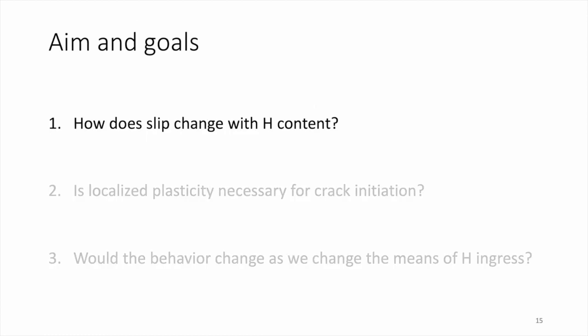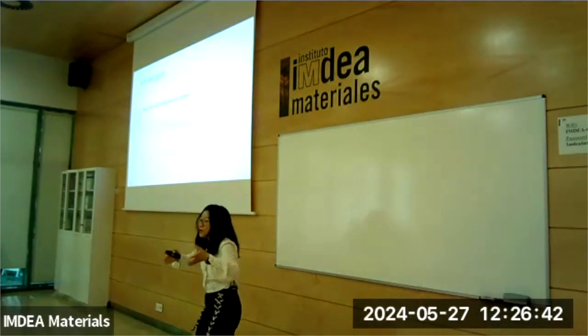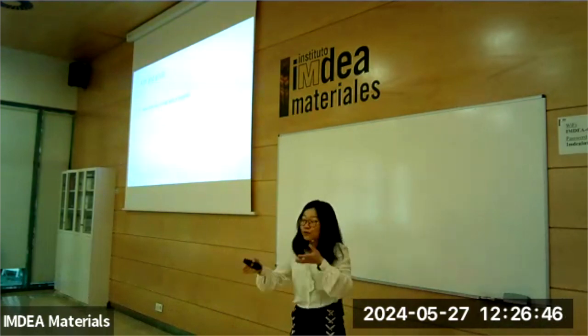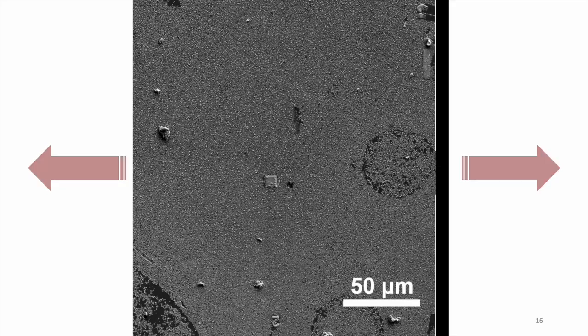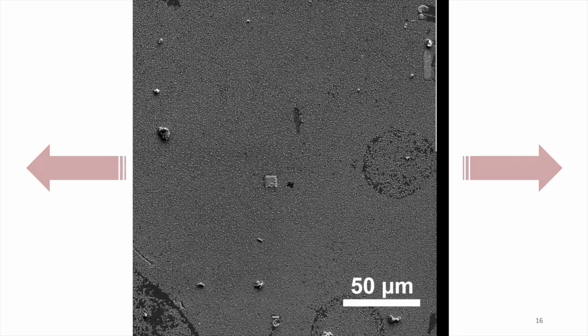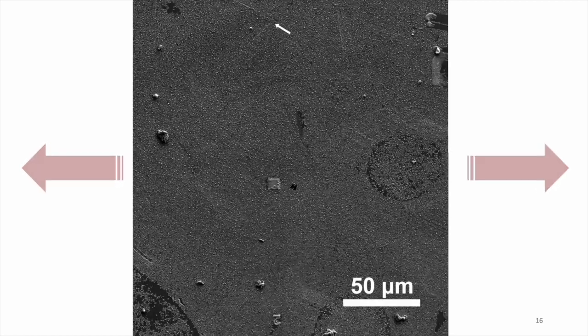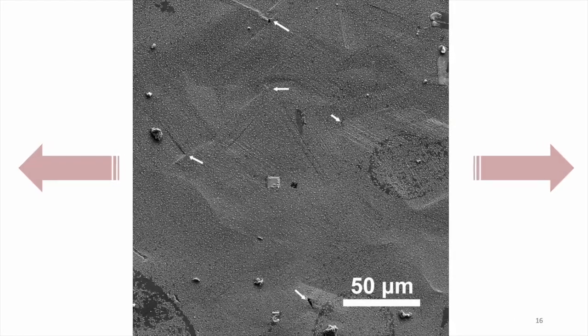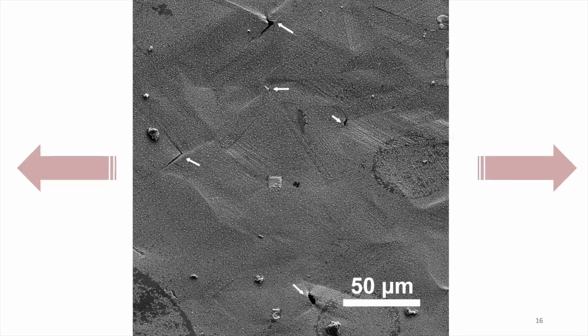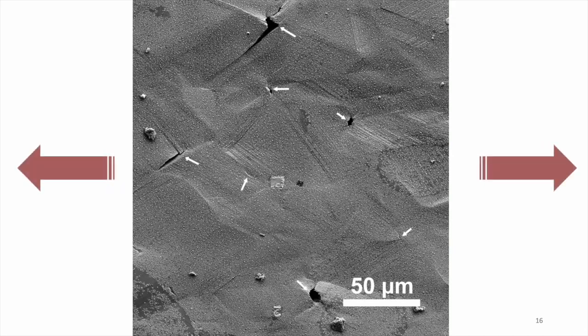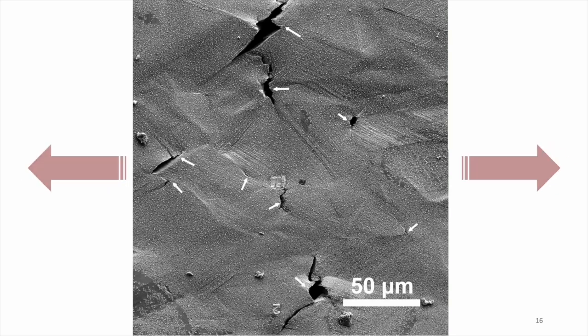Going back to our main goals, we want to know how the slip changes with hydrogen content. We know we can see surface slip under SEM, and we see more surface cracks in the electrochemical charged sample. So to better understand this question, maybe we should focus on the electrochemical charged sample and look at how the slip changes with hydrogen content. We observe the surface of the electrochemical charged sample in situ in the SEM while doing the tensile straining. We'll be able to see the crack initiation, and the white arrow is pointing at the initiation site. This is a sample with the medium hydrogen content, and you see nice surface crack initiation in this case.